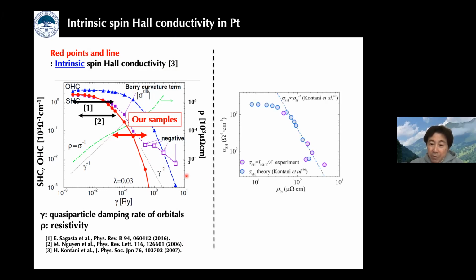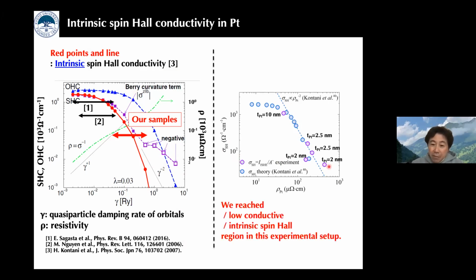In fact, when we replot our experimental results about the estimation of spin Hall conductivity by changing the film thickness, the results can be nicely reproduced by the theoretical calculation. And from this result, we can conclude that we control the spin Hall conductivity by the gating. Because we use the low conductive platinum, the platinum film is within the intrinsic spin Hall regime.